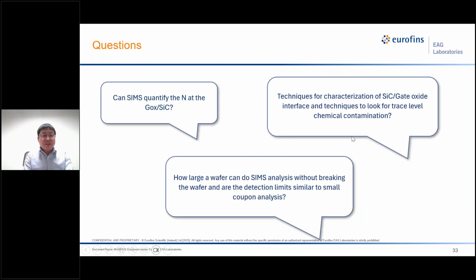So here are some questions related to the SIMS capability. Can SIMS quantify the nitrogen at the interface of gate oxide and silicon carbide? Techniques for characterization of the silicon carbide gate oxide interface, and techniques to look for trace level chemical contaminations. How large a wafer can do SIMS analysis without breaking the wafer, and are the detection limits, similar to small coupon analysis.